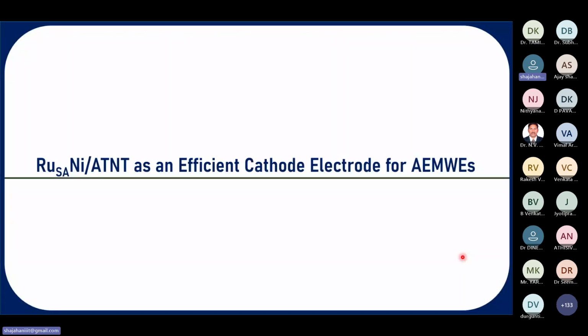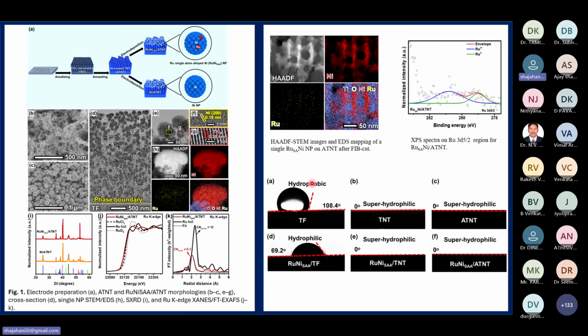So after we made that one, we also prepared, like initially we prepared the anode material. Later we also prepared the cathode one. So in that cathode one, obviously we need to make an advanced one, right? So ruthenium single atom doped nickel, as an efficient cathode we prepared for AEMWE. So with a similar method, the electrodeposition method, we prepared the ruthenium nickel single atom catalyst on the substrate. Similar results: it is hydrophobic, and after depositing it becomes super hydrophilic, and this result also confirms the successful formation of ruthenium single atom nickel on the substrate.